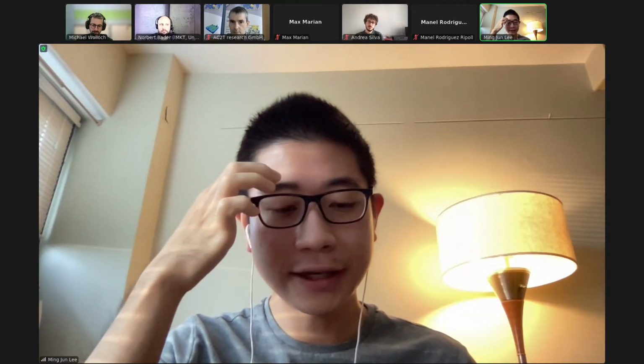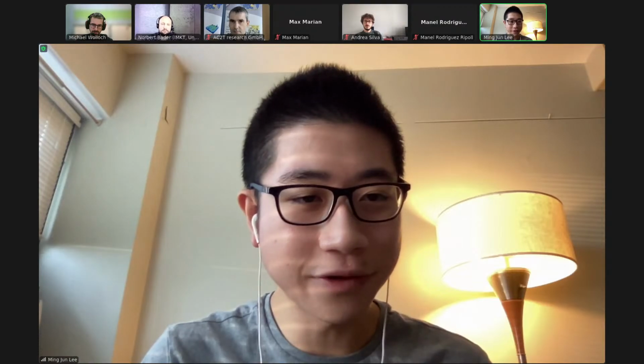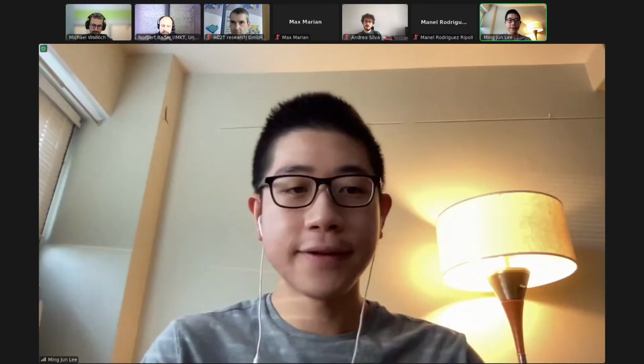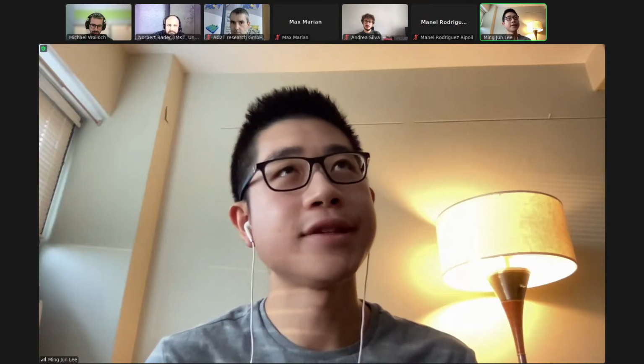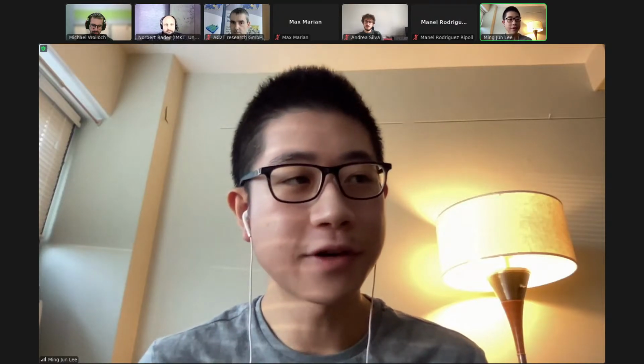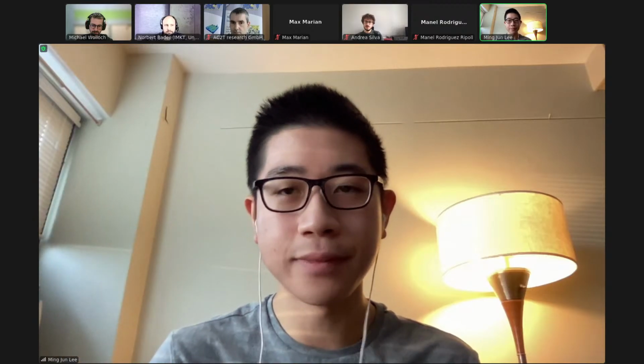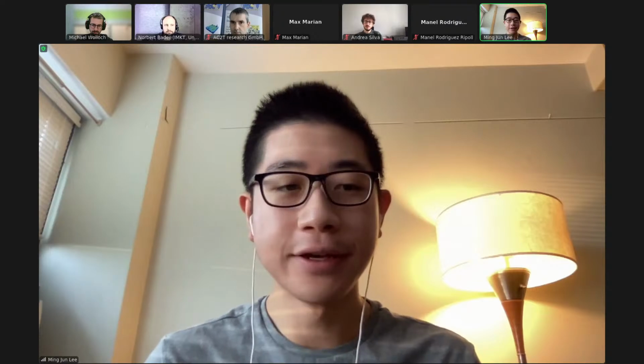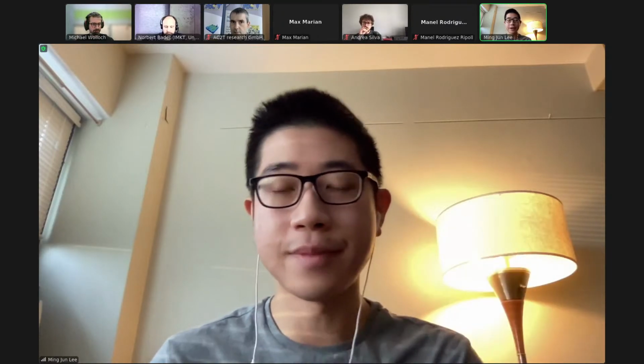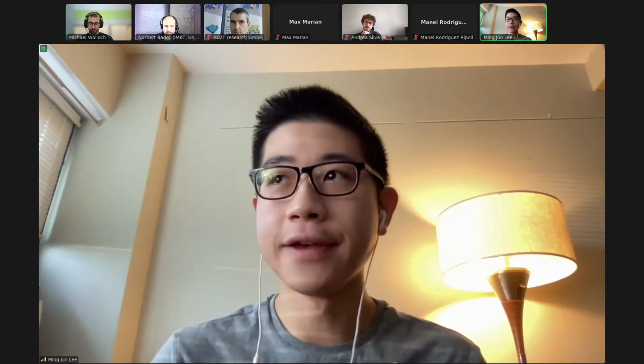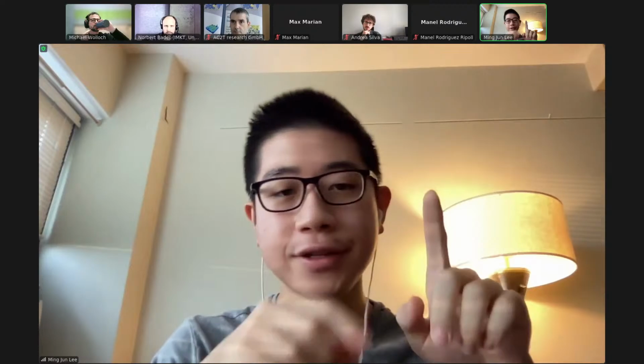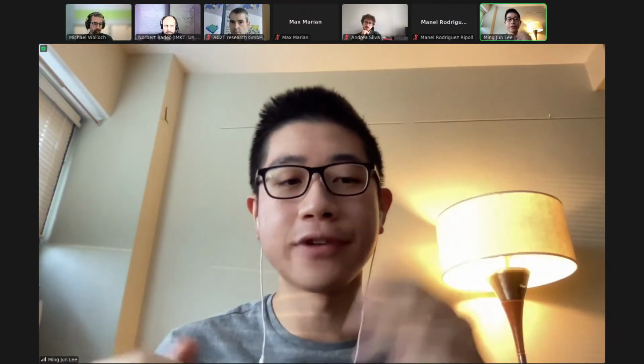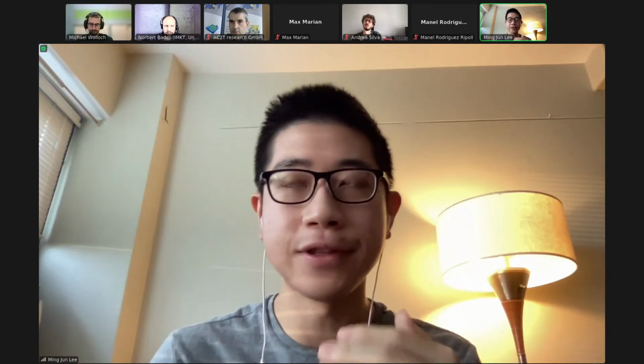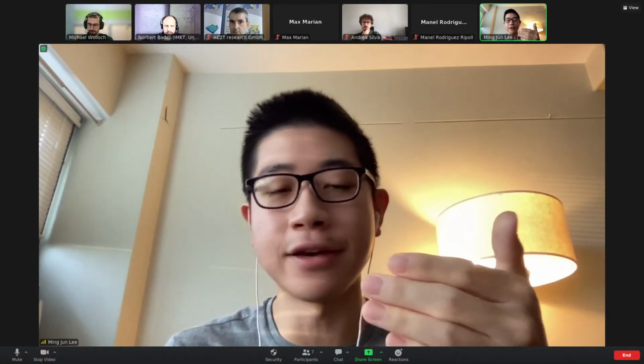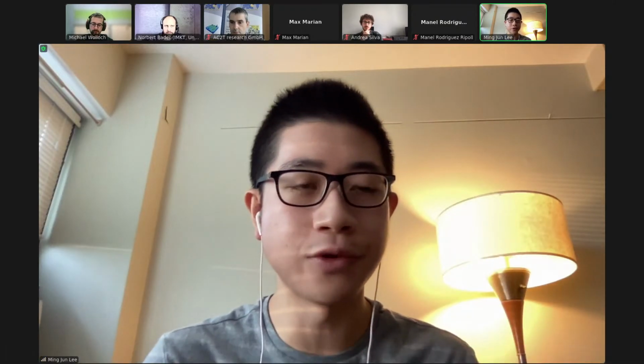And regarding the second, you mentioned calculation of the friction properties. Is there a calculation or a model? I believe in 2018 and 2020, one of my seniors in the lab, Tuba Shoaib, who has already graduated, studied specifically the physics of friction on polyacrylamide hydrogels. And what she showed was that there is actually a U-shaped relationship of friction against the sliding velocity. So at slow sliding velocities, the adhesive interactions between your gel and your measurement device, in our case the AFM tip, are the predominant contribution to the friction force.